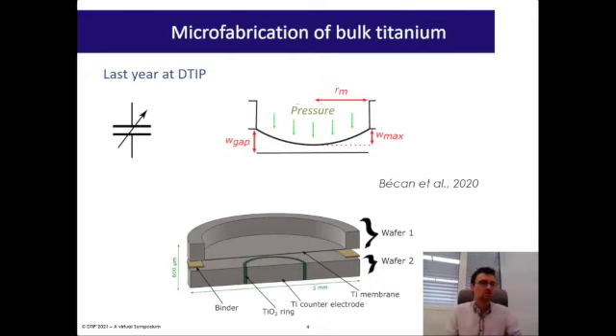At the last session of DTIP, I presented the design of the pressure sensor with a titanium transducer, which is a capacitive pressure transducer composed of two parts. The first one is a titanium membrane, which is sensitive to pressure, and it will deflect when pressure is applied here. This membrane gets closer to its counter electrode here, and it will induce a change of capacitance.